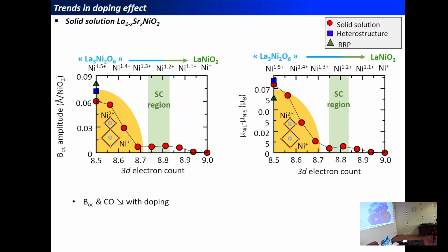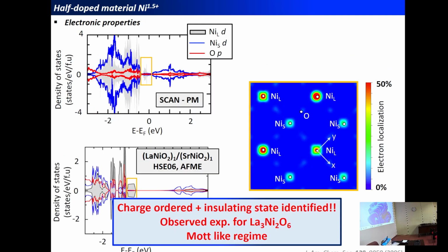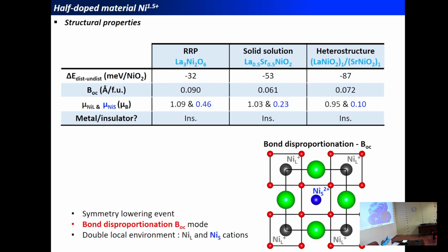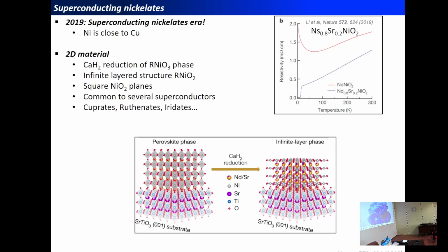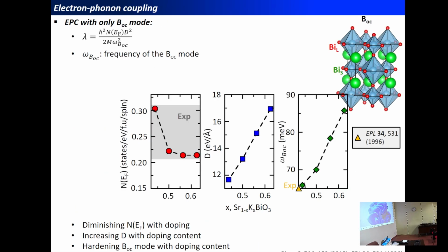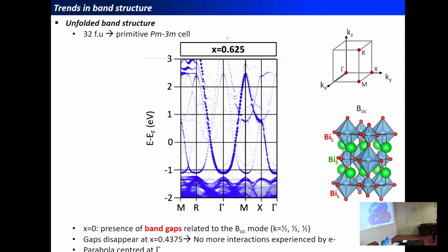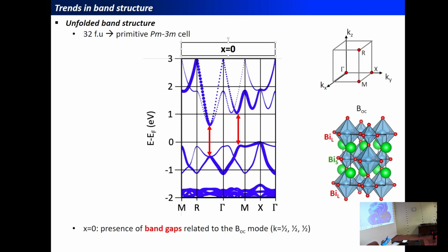I didn't see this one. And also, when you discuss this breathing mode and the direction from gamma to the 1/2, 1/2, 1/2, one can see also a gap from gamma to M. Does it have any role? It's the same amplitude in fact. Let's go back. So I just look at this slide. You see, it's the same magnitude. It's just shifted along gamma-M. It's closer to the M point because when you project in the plane, the cross section will be at a different position than just the 1/2, 1/4 there. But it's the same gap that is open, because it's the breathing distortion that does that.